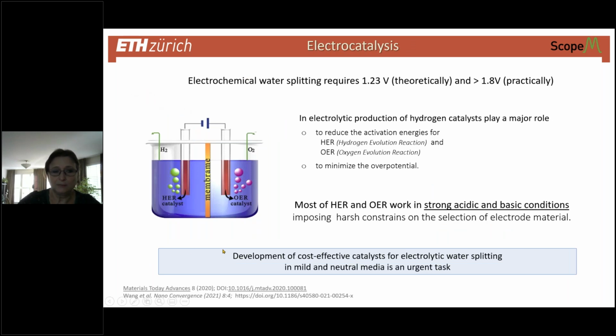The electrochemical water splitting reaction theoretically requires only 1.23 volts, and in practice it's quite a bit higher, and therefore catalysts are required. This electrochemical water splitting reaction can be seen as two half-cell reactions, the hydrogen evolution reaction and the oxygen evolution reaction, both developing at the electrodes immersed in the electrolyte, separated by the membrane.